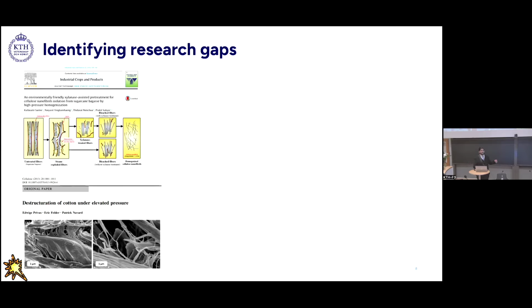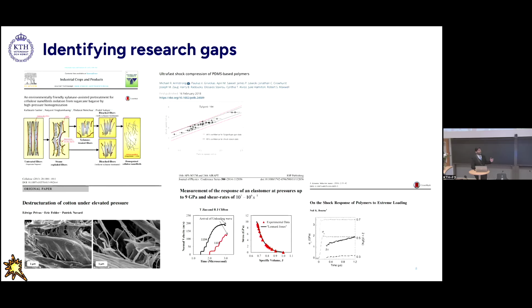Also, there was one more research which tried to treat the cotton pulp with extreme pressure and temperature conditions, and that basically destroyed the cotton fibers. A few more researchers have highlighted treating elastic polymers with shock waves, and the result was, along with the high compression wave, they also have a shear wave associated with it, which is a very promising thing for us to start with.